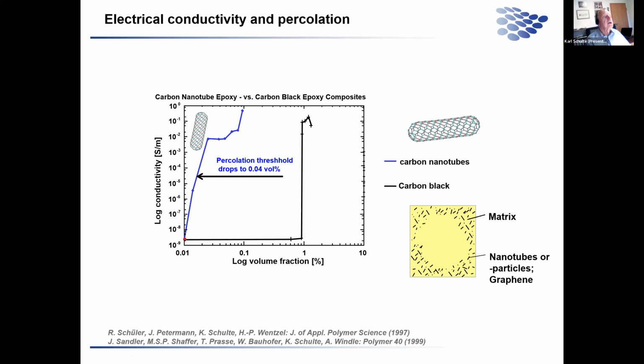If we now go away from carbon black, which are rather large micro-sized particles, to carbon nanotubes, we see a result with carbon nanotubes. Just by changing to carbon nanotubes, the percolation threshold level drops from 0.9% to 0.04 volume percent.